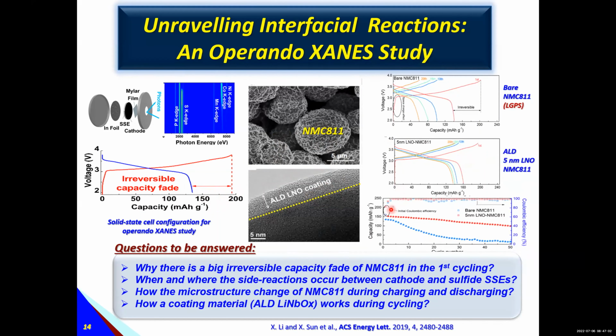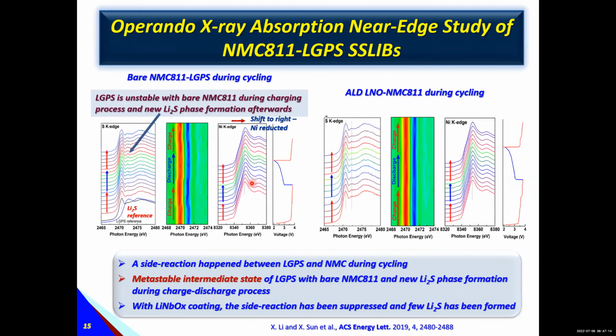So in this case, we need a similar battery to test without coating and with coating. From here, we can see the big difference. What happened at the interface? We're using in situ XAS study. During the charge, we found some new compounds corresponding to lithium sulfide. And also we found nickel K-edge shift, indicating nickel is reduced.